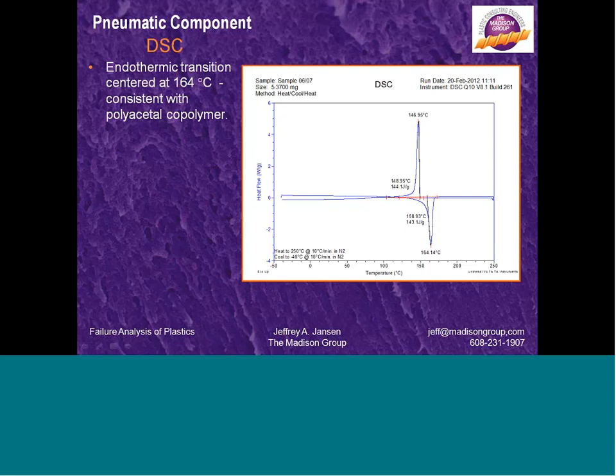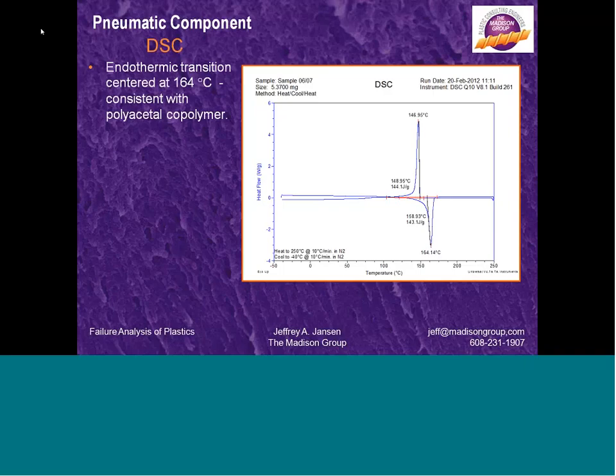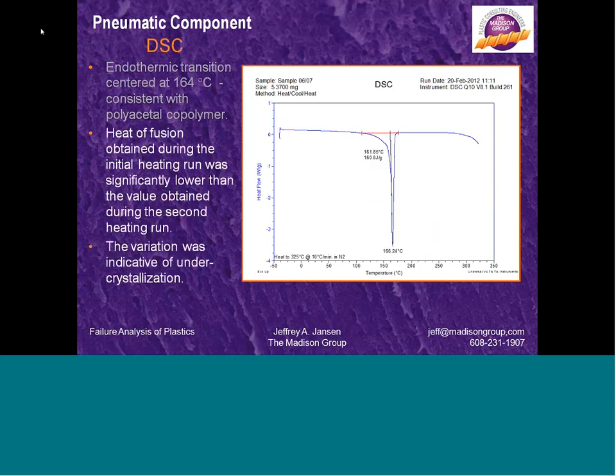The other significant piece of information we get here is the heat of fusion. In this case, it was 143.1 joules per gram. That's the energy required to melt the material. And since only the semi-crystalline material will melt, it's really an assessment of the crystallinity of the part. We take that and we heat it, and then we control cool the part, and then we heat it back up through melting a second time. And the heat of fusion here was significantly higher, 160.8 joules per gram, indicating that the part was undercrystallized as molded. So it was probably molded in a relatively cold tool, and the material was not properly crystallized, which will